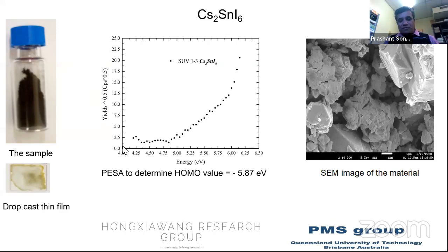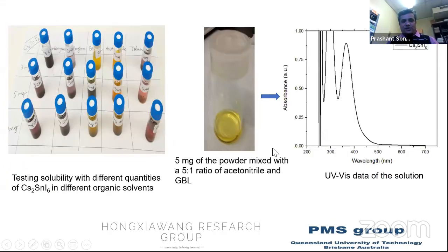He faced a problem making devices, because these are very hard inorganic halides, and they don't have the ability to form a nice film as compared to other perovskites, like the methyl ammonium lead iodide I was showing you. Those are organometallic, meaning they have some methyl or alkyl group there, which gives them the ability to form a film. But if you remove the alkyl group, these are pure inorganic halides, like cesium, tin, and iodine, both inorganic. There is no organic component, so they are very hard to get as a thin film, and that was one of the biggest challenges.